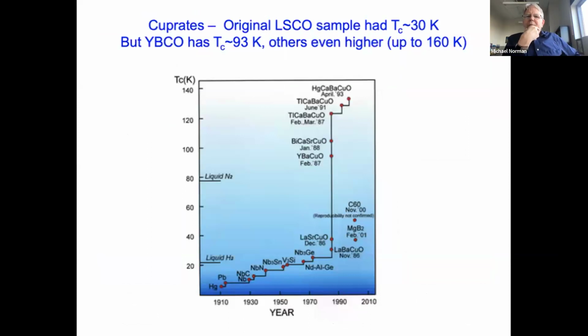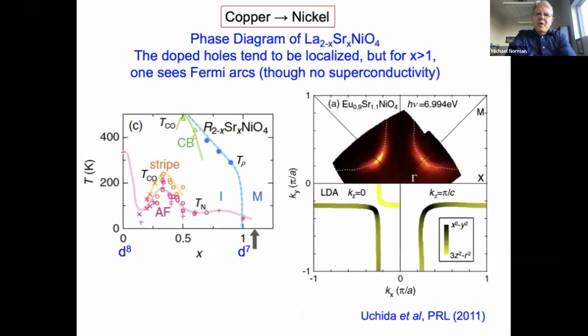So, when cuprates came out, by today's standards they're not that high, 30 Kelvin, but it didn't take long to go up to 160 Kelvin. Since then, people were thinking about whether there are cuprate analogs out there. And obviously, one of the first things that people thought about were nickelates. And for the 214 nickelate, as usual, hole doping is always easier than electron doping. And so the first thing that was explored was the hole-doped side of the 214 nickelates.